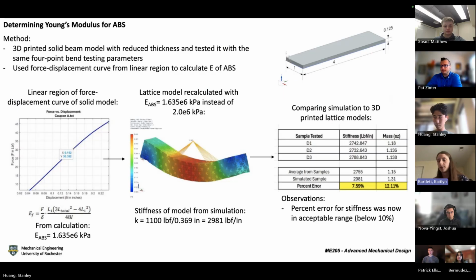And this one is not shelled. It's completely solid. So we put it through the same 4-point bend testing as the previous models, and we got the force displacement curve again. Then we calculated the Young's modulus with this equation that is used for 4-point bend testing. Once we got this Young's modulus, we used it for the 7-inch models that we did previously, and the percent error was drastically reduced to under 10%, which is considered acceptable. So that was definitely an improvement.